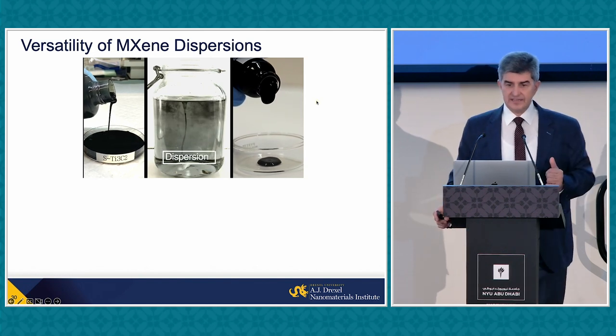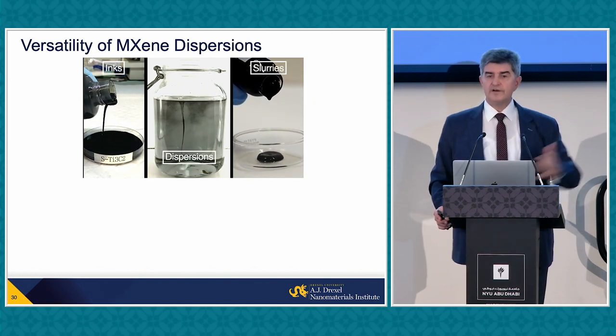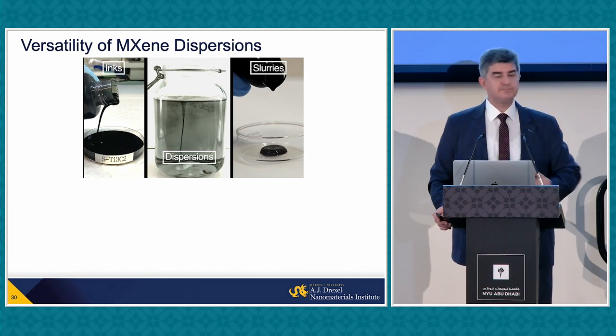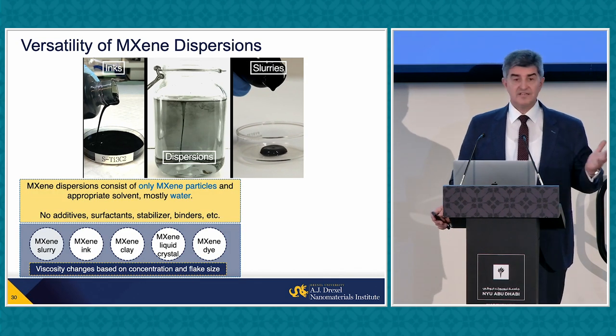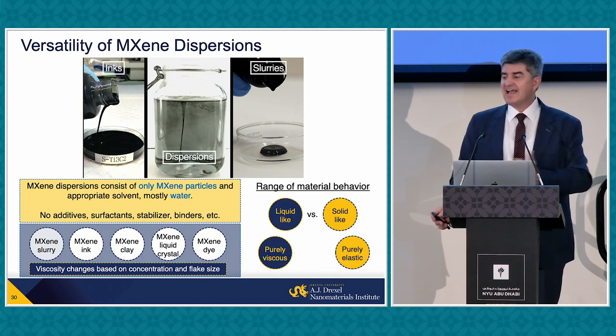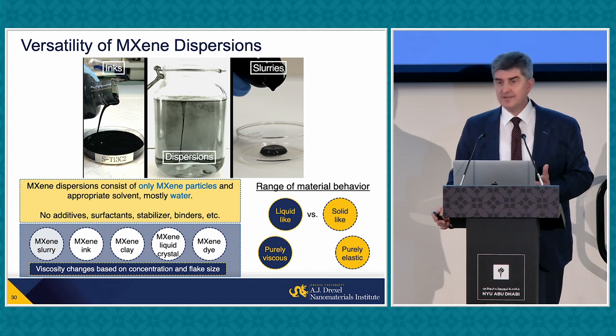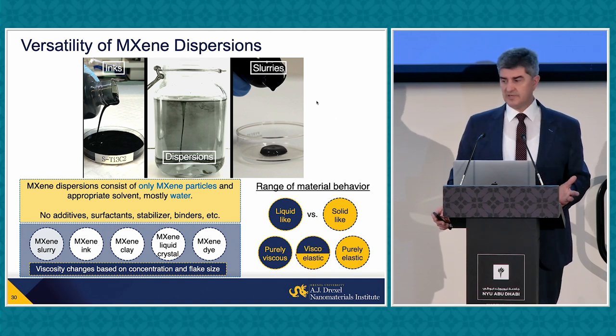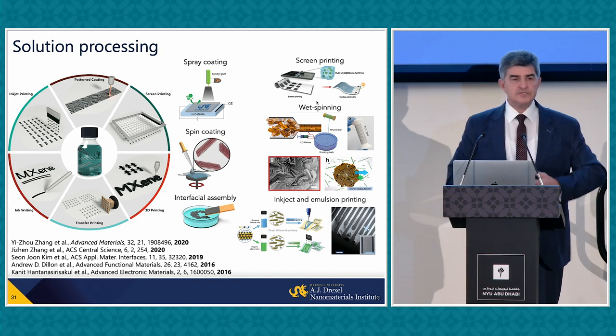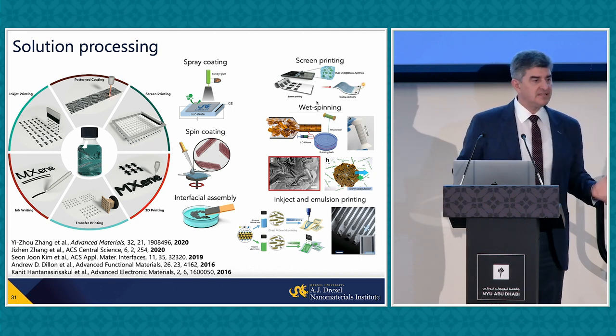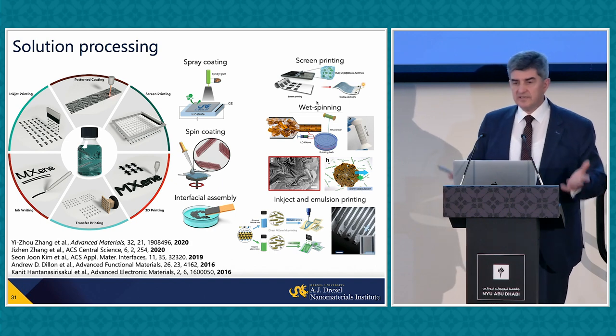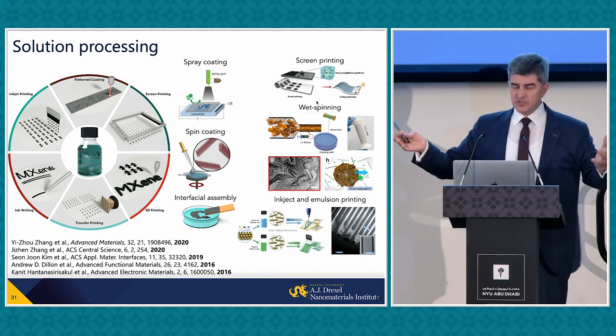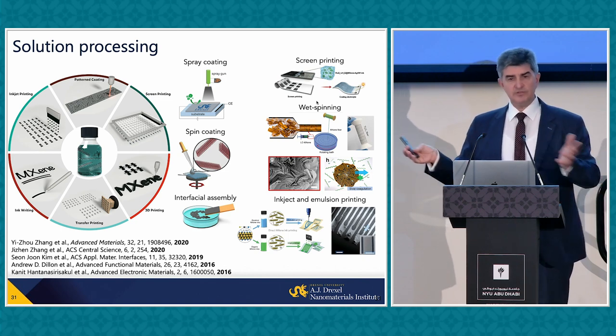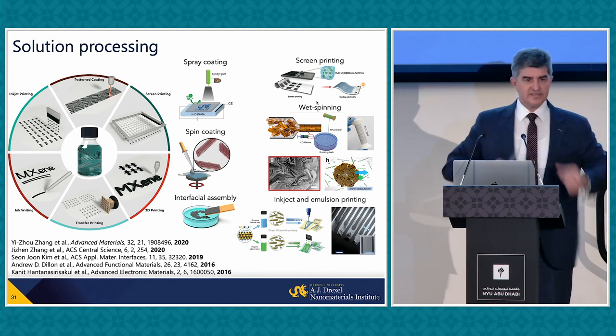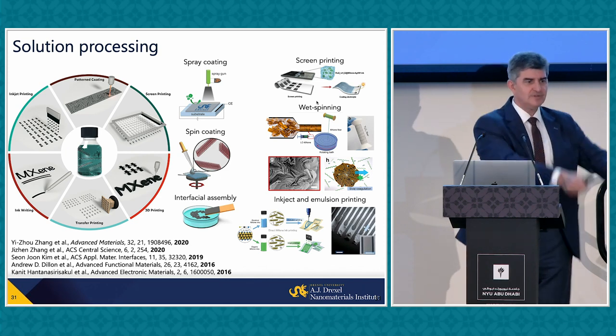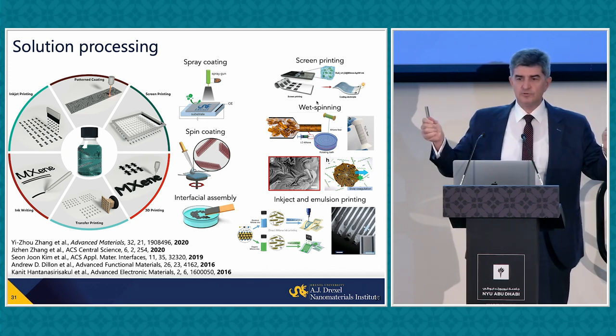It's a liquid crystal, and you can draw fibers, or you can make films by doctor blading, for example, spreading it over the surface. And just by controlling the size of the particle, concentration, water, we can get any concentration. Why is it important? Because now we can manufacture out of it. We can make films, we can make three-dimensional foams, we can pattern, we can use any known technique: 2D printing, 3D printing, 4D printing, changing other parameters in time, spin coating, blade coating, dip coating. You can take your T-shirt, dip it into a dispersion of MXene in water, take it out, and